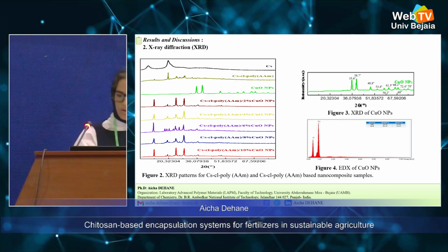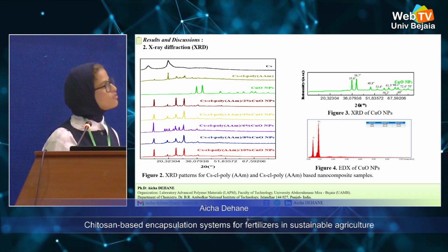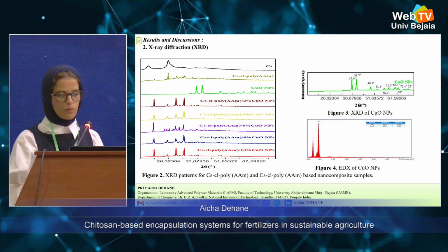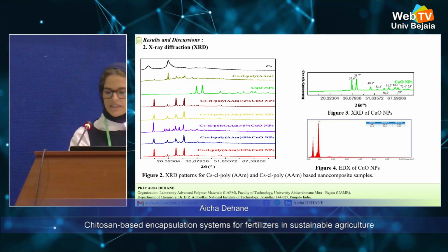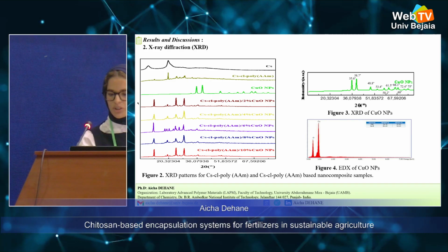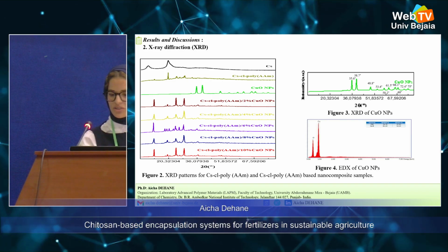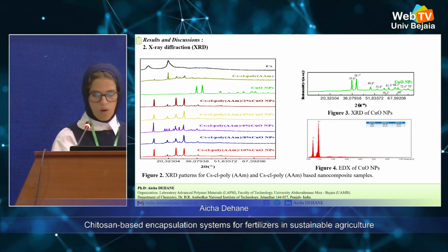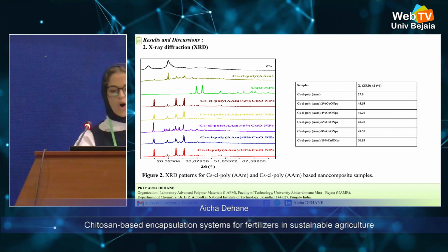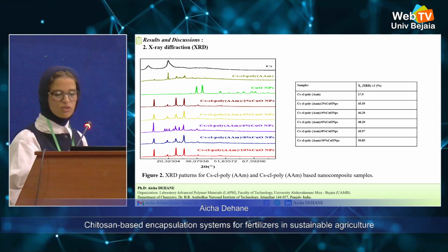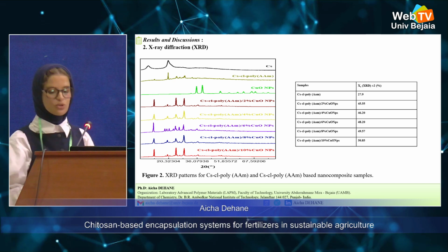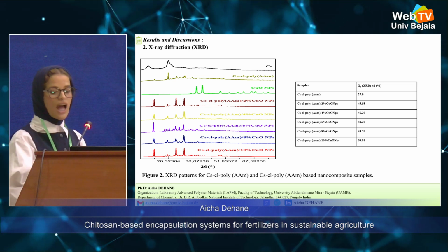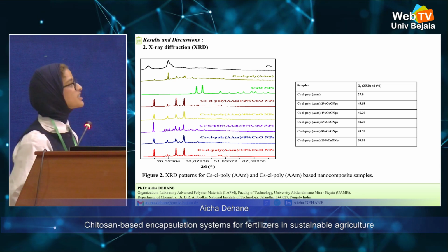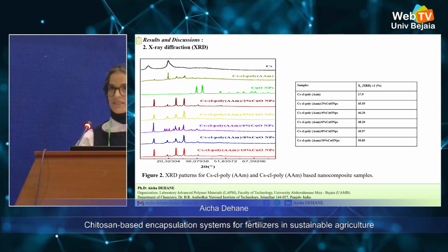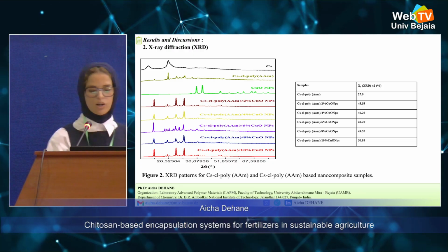XRD confirmed the grafting of acrylamide onto the chitosan backbone, with a decrease in crystallinity compared with pure chitosan, which indicates the grafting reaction. Also, XRD gives us confirmation of the incorporation of CuO nanoparticles into the chitosan matrix, and the degree of crystallinity increases with loading of CuO nanoparticles.